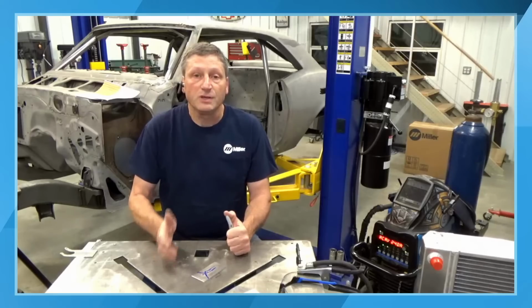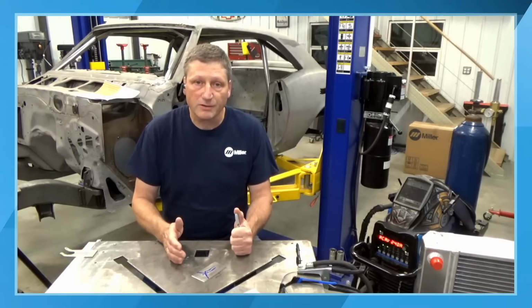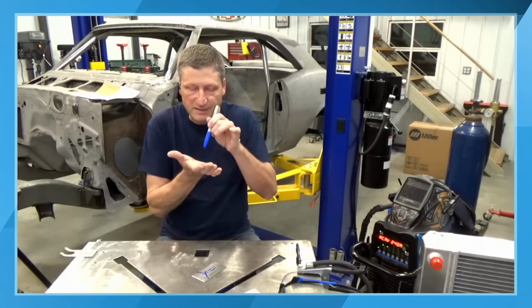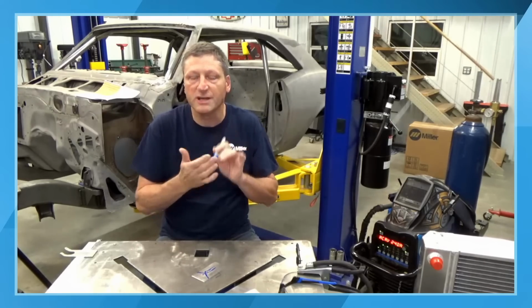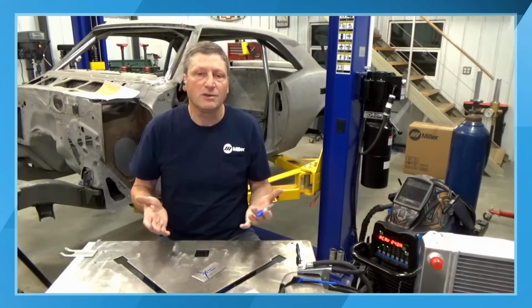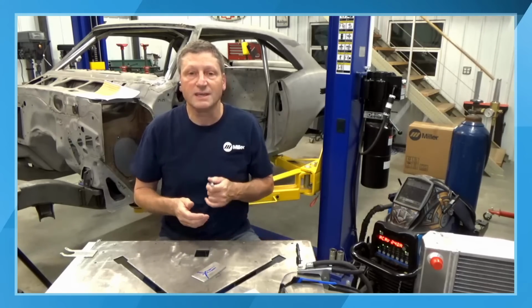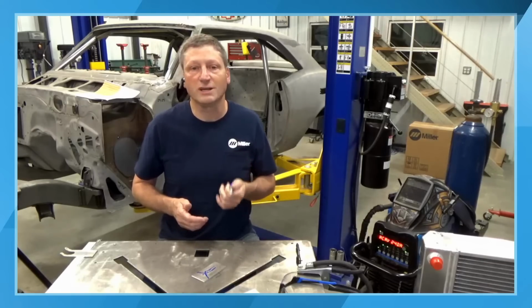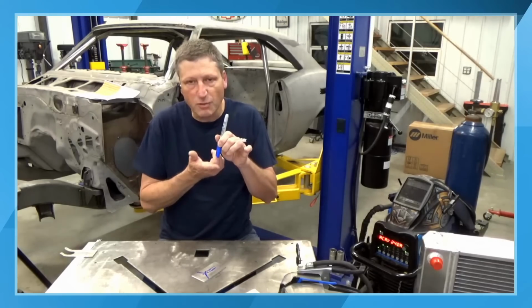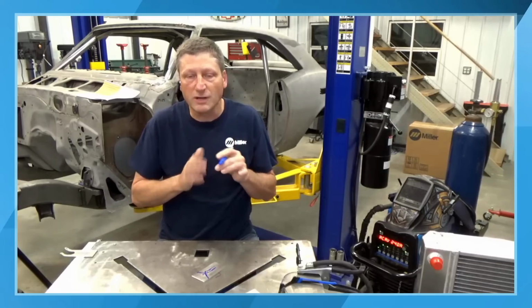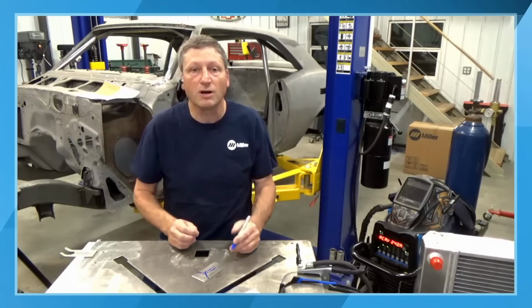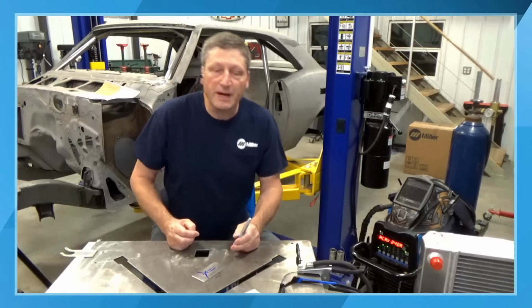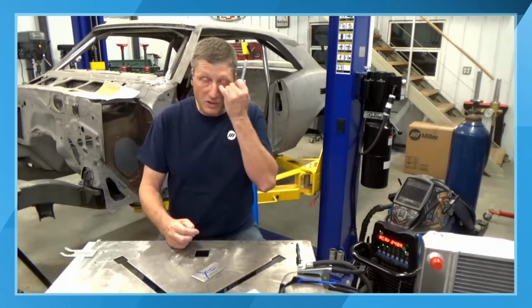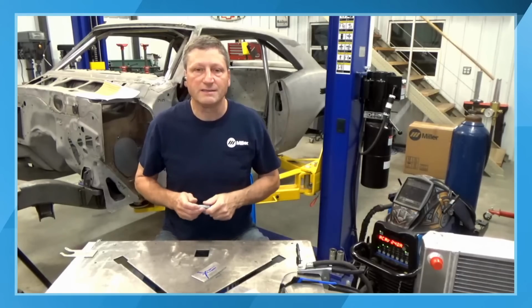For aluminum, you still grind it to a point on the inverters. You can take it and just knock that point off, just snub it off a little bit. If you don't do that, it's not a big deal. The amperage that you are using on your machine will cause that point to just pull up a little bit, so it may form a real tiny ball on the end of it. But I like using the ceriated because it's an all-purpose tungsten. I can run it on AC and DC.